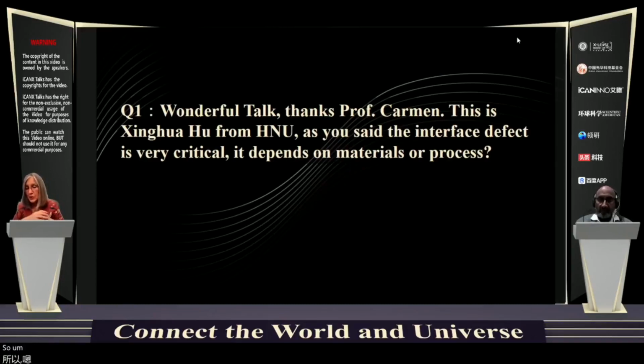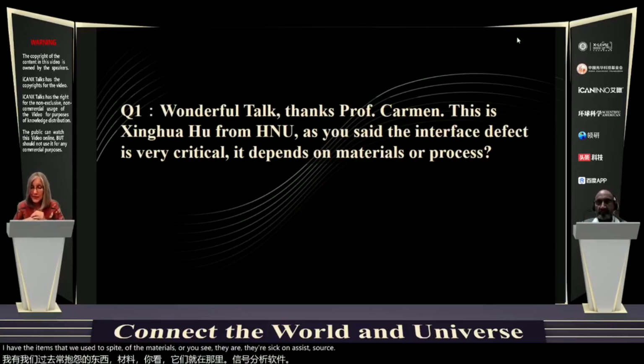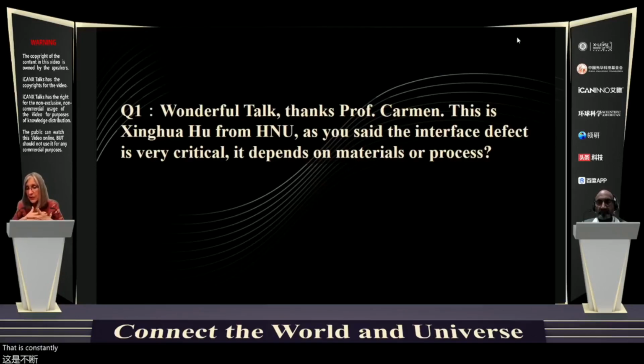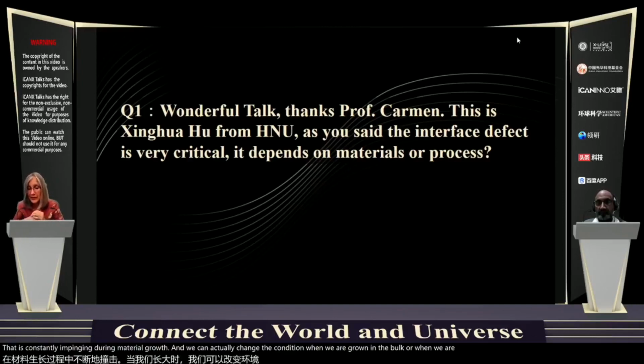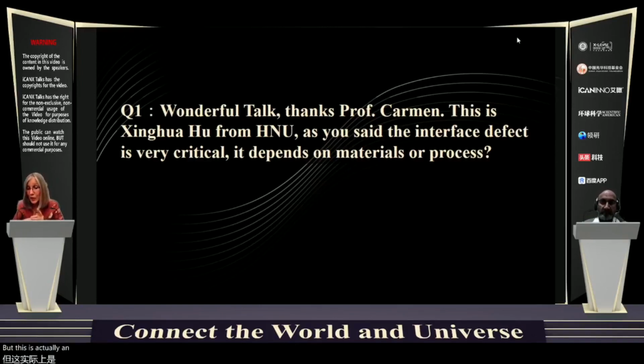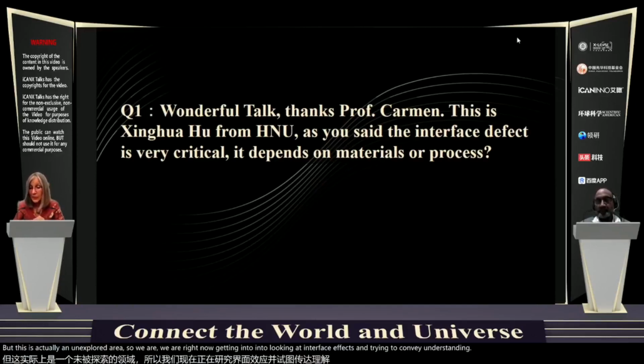So yes, this could be altered by process. And we do that specifically by changing the energy of the ions that we use to sputter the materials, or by using the second assist source in our system that is constantly impinging during material growth. And we can actually change the conditions when we are growing the bulk or when we are growing the interfaces. But this is actually an unexplored area. So we are now getting into looking at interface defects and trying to understand their role and to control them.